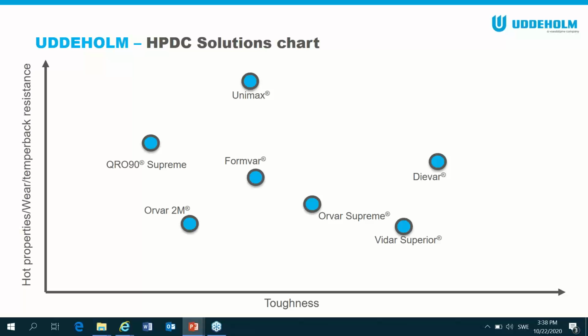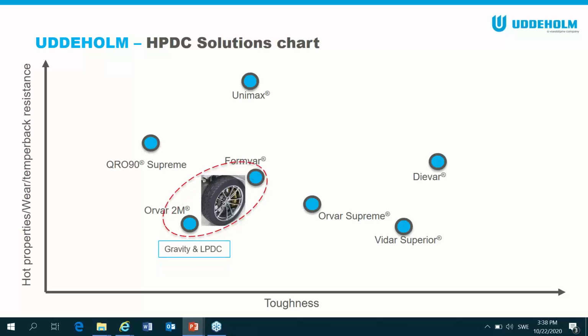So how do we place these materials? There's two there that I haven't mentioned, but we're focusing mainly on high pressure. I put them here just in case there are some low pressure or gravity casters listening. So we do an Orvar 2M, which is an H13 type material, and we do Formvar. Now, Formvar is a non-ESR version of Dievar, and it doesn't have the same processes of Dievar, so it's not as tough. But it benefits from all of the hot properties that Dievar's got. So high hot yield strength, temper back resistance, and so on.